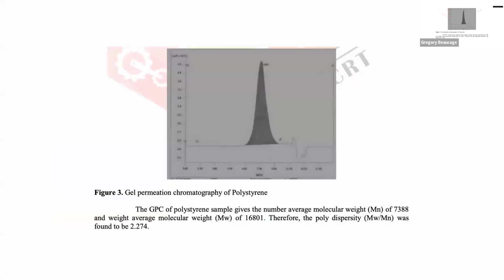Anyway, if it's anionic polymerized, you get a spike, and for a free radical, you get a broad distribution. So commercial polystyrene would normally be a fairly broad distribution of molecular weight. You measure that by Mw over Mn, which is called the polydispersity index. That would be 1, or 1.02, for anionic polymerized. For this commercial free radical polystyrene, it's 2.2. And for polyethylene, like high density polyethylene, it can be 15.